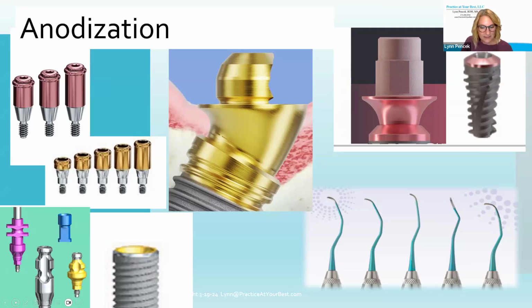And we find in implant dentistry, one company has a pink anodized implant, and they say that it gives a nice aesthetic because it blends in with the soft tissue. We have a gold aesthetic with the anodization, and we found the surface chemistry with the gold anodization gave better biointegration, faster osseous integration, faster mucosal attachment. So we actually have a faster response.